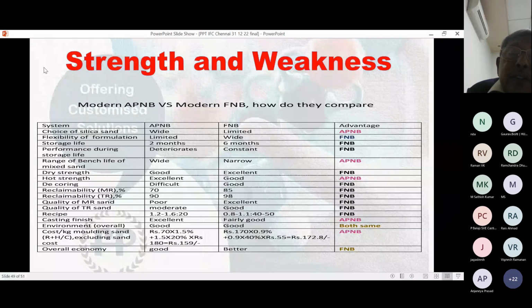Among recent Furans we have seen, I cannot quote the names of the foundries, but people have made castings with Furan, up to 15 tons of steel casting, and another foundry is making regular 2 to 5 tons of steel castings using the latest version of Furan. And I have seen the castings; they have excellent gloss. If you compare the castings at a practical addition level, they are more or less the same. So overall economy is good in the case of Alphaset, better for Furan.